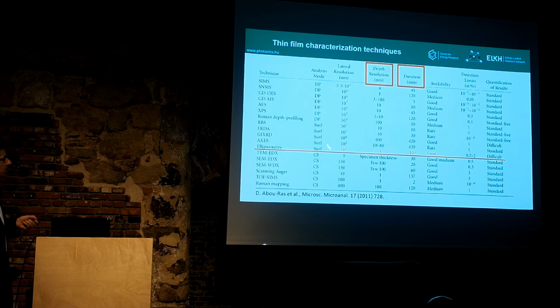Here, there are three groups. The DP means depth profiling. It means that we remove parts of the layer, either by sputtering with ions and thinning the layer, and we measure either the particles that are removed or the remaining surface of the layer. The typical features are shown here: the lateral resolution is usually not very good. The depth resolution is usually good, in a nanometer range, and the duration is quite long.